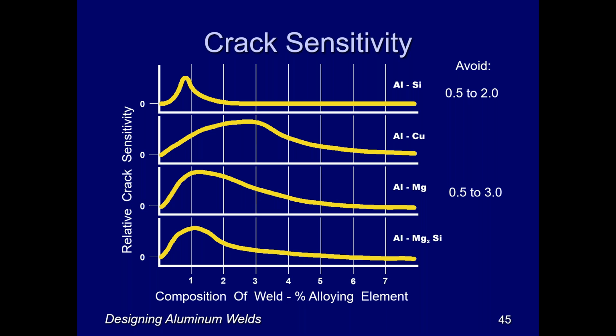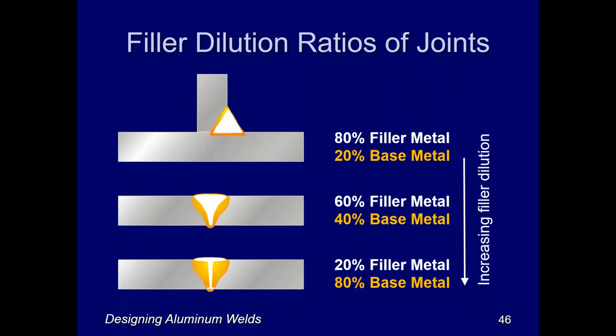And so if you can anticipate what the dilution will be in your joint, then you can anticipate whether or not you'll be in that crack sensitive composition. Just to illustrate it, you have very little filler dilution in a fillet weld, as you can see on the top of this figure, and very high dilution of the filler metal at the bottom here, which is a square groove weld. And a V groove in between is going to have a dilution of the filler metal somewhere in between a fillet weld and a square groove weld.